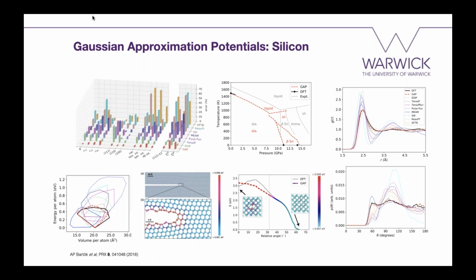So the red lines are our simulations, and indeed they match up quite well with DFT, and it can be regarded as a DFT quality phase diagram for silicon.